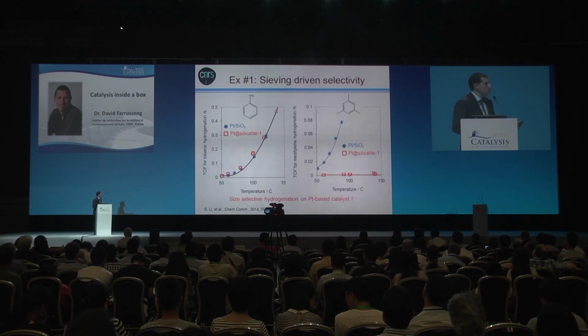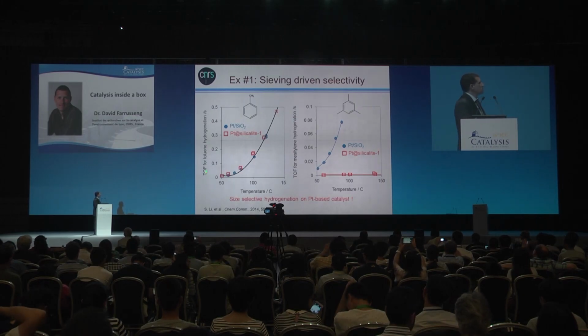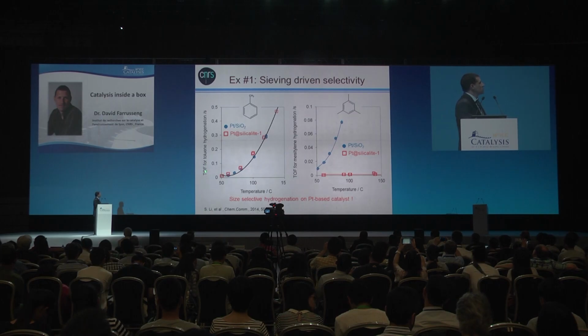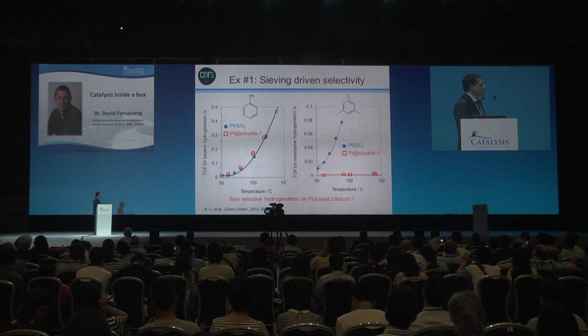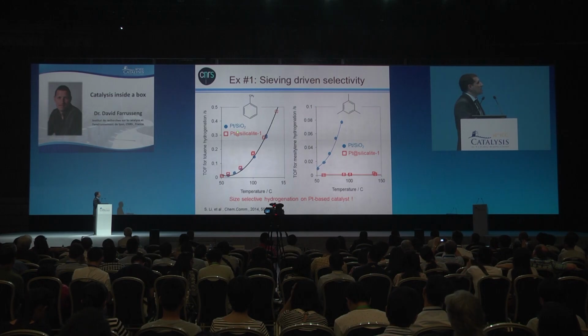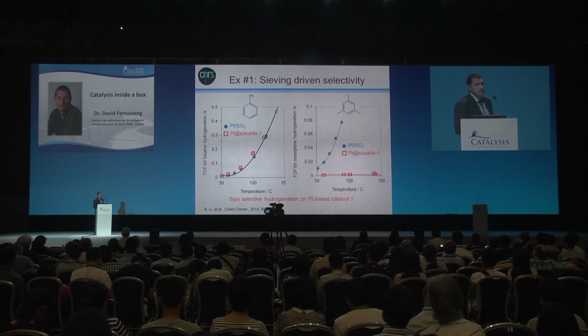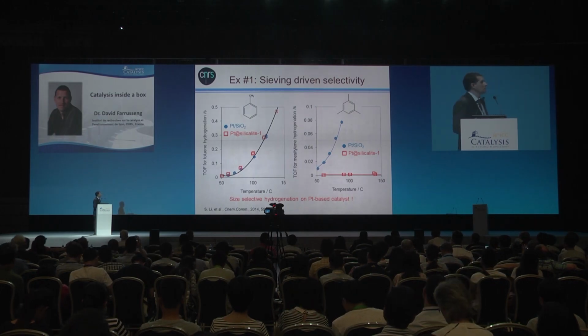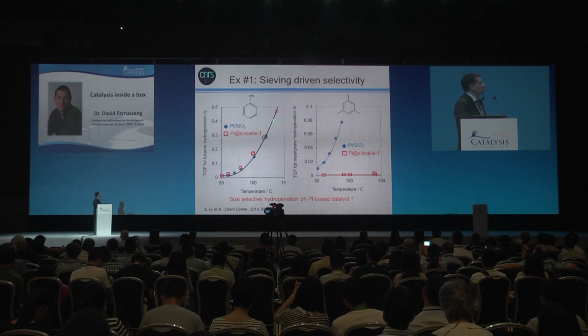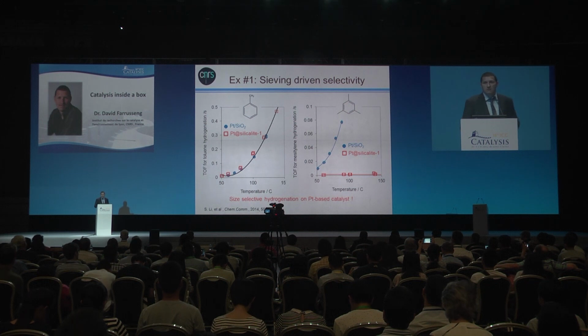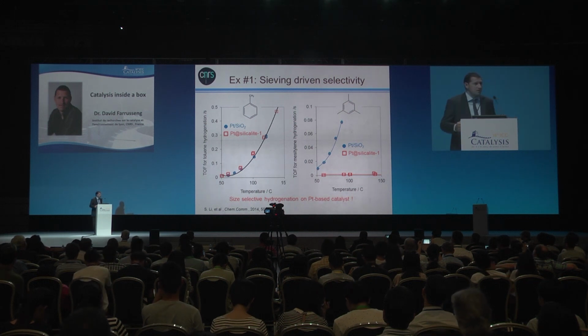So if it's true, then we can do a selective hydrogenation. What you can see here is the hydrogenation activity of toluene as a function of the temperature. We selected platinum silica as a standard material. You see here that our platinum encapsulated in silicalite 1 behaves the same as the normal catalyst.